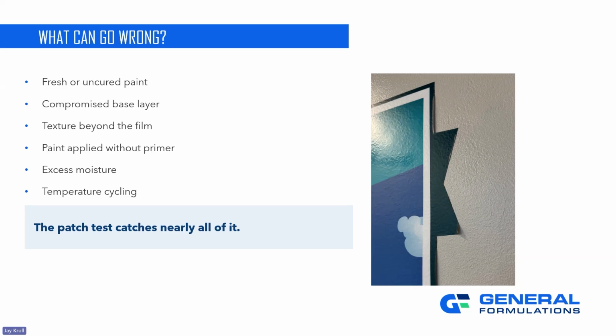until you lift up the paint and tape, or the patch test, right? Is there excess moisture in the wall or in the room? Those are going to impact the anchorage. We just saw this a couple weeks ago, where it was the anchorage of the skim coat to the drywall underneath that was then primed, and within 2 hours after the primer, because it was dry, they applied a graphic over top of it. And the primer had re-wet the skim coat, which wasn't cured on its own. When they lifted, the skim coat came straight off the drywall. That excess moisture was still in that wetted skim coat, even though it hadn't cured. These different layers require a little bit of time.